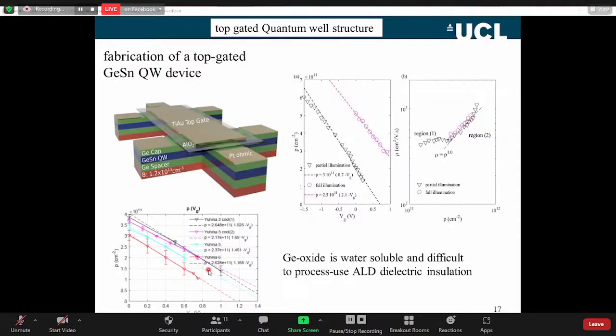The slope of this line is the capacitance. Think of it as a parallel plate. That slope is telling you about geometry. What's different with germanium compared to silicon is that germanium doesn't have a very nice oxide. The whole electronic industry was built around silicon dioxide being a nice gate dielectric. Germanium doesn't have that. Germanium oxide, the natural oxide on the surface, is water soluble. Well, that causes major problems for the electronic industry. However, with this thin ALD, we're able to make devices.